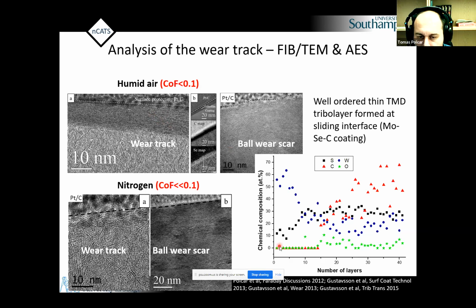As you can see here, for example, this is like a depth profile using Auger, or in this case, I think XPS. And you can see that at the surface, there is no oxygen, no oxidation, which is quite interesting itself, and no carbon as well. So there is some specific effect when you separate the solid lubricant phase and you make it very nicely ordered there. And then we tried it in humid air, we tried it in nitrogen, different environments. We always end up with the same conclusion. We produce this very interesting solid lubricant crystalline transition metal dichalcogenide on the surface.